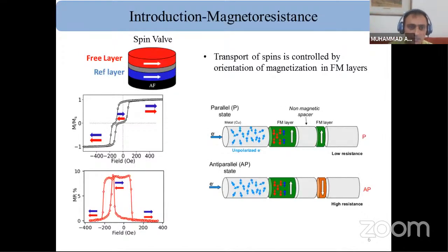A spin valve is comprised of two ferromagnetic layers, one called the free layer and the other called the reference layer. The reference layer is pinned with an antiferromagnet to fix its coercivity so that in operation it will not change its direction. Here you can see a free layer.